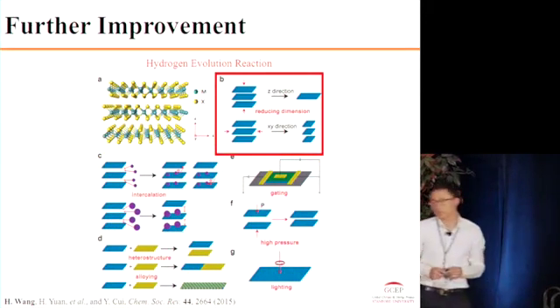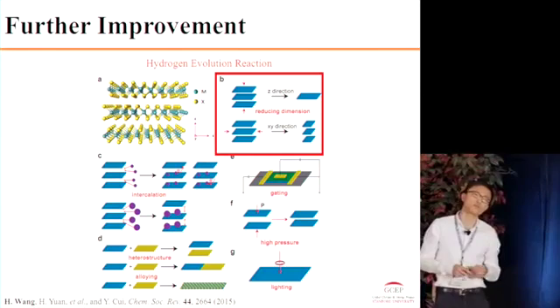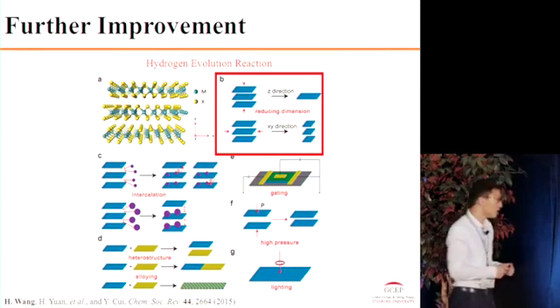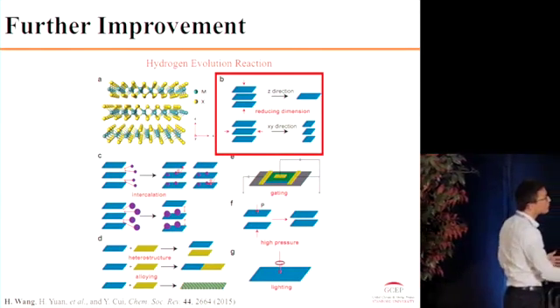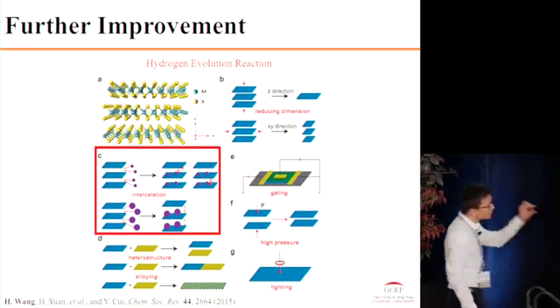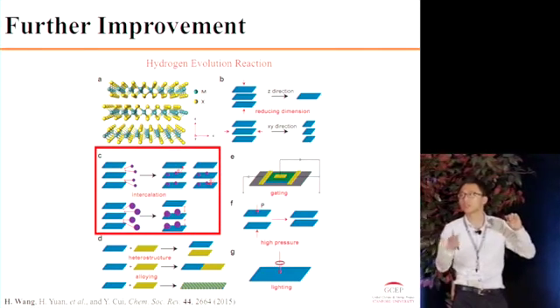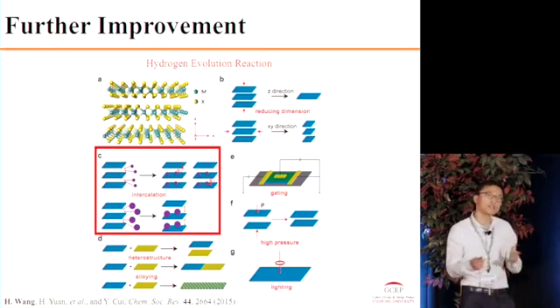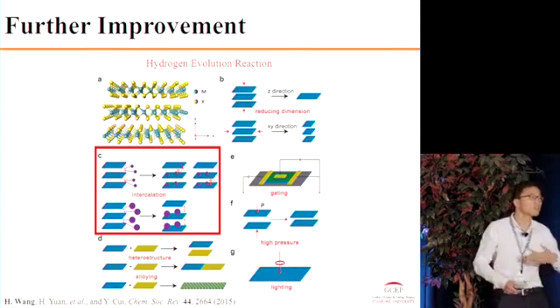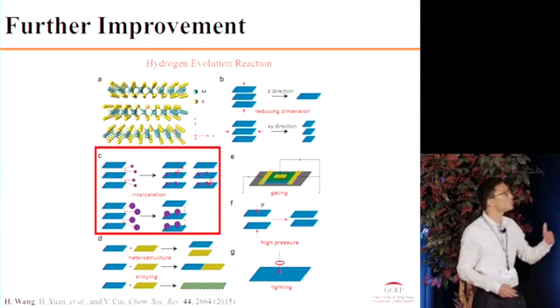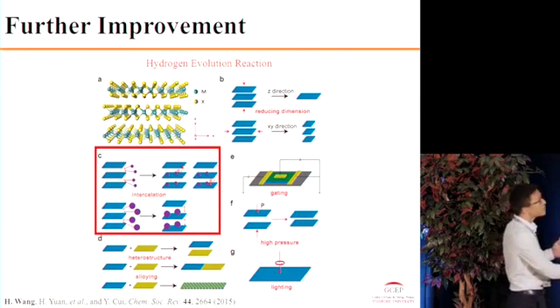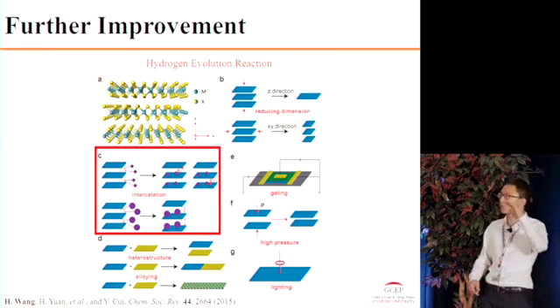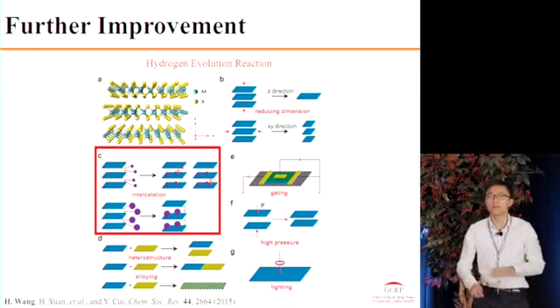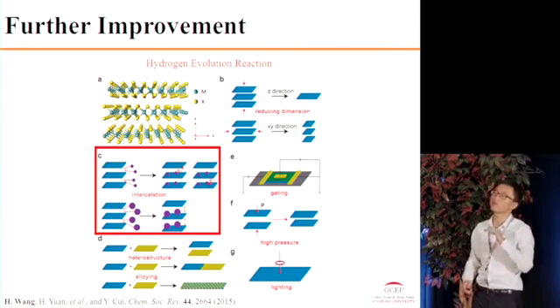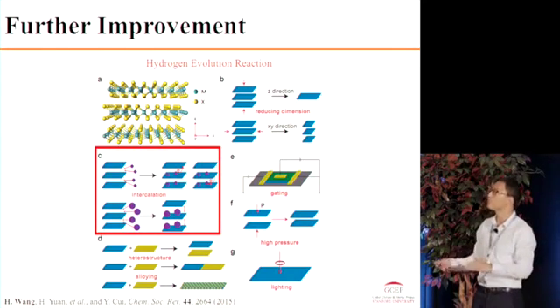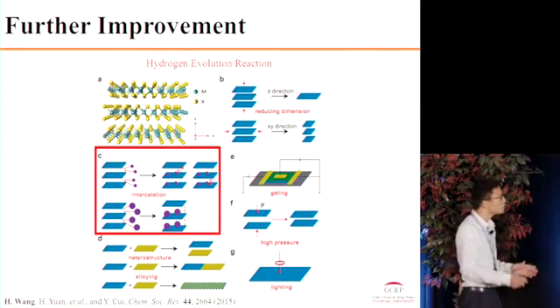And if we look deeper into the electronic structure of the molybdenum disulfide, how can we improve this catalytic activity further? As we can see, this unique crystal structure allows us to intercalate a lot of guest ions. Those guest ions, for example alkaline metals, can contribute a lot of electrons into the layered structure. And this charge transfer will significantly tune your chemical potential, your electronic structure. And with well-controlled electronic structure, we can improve our catalytic activity in a controlled manner.